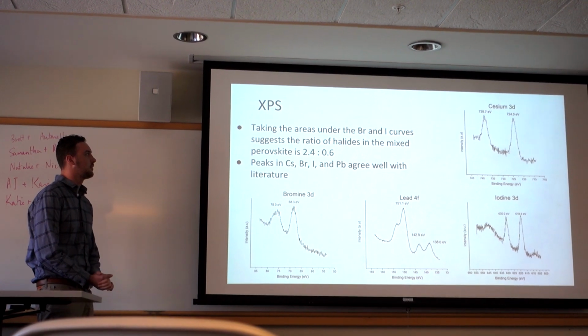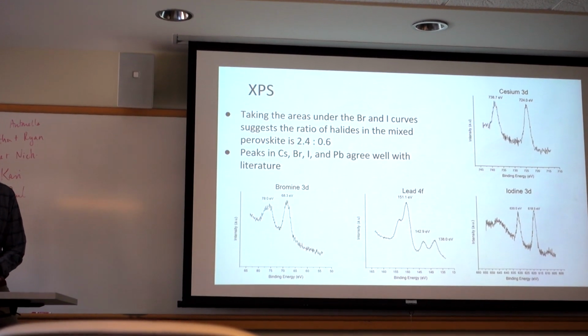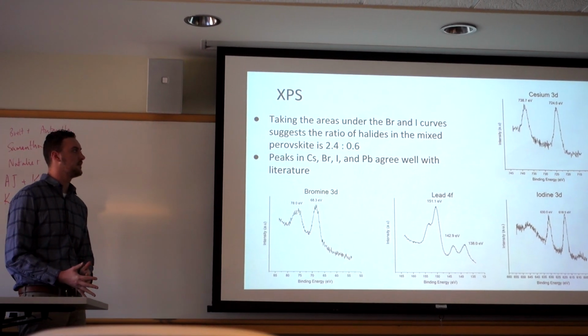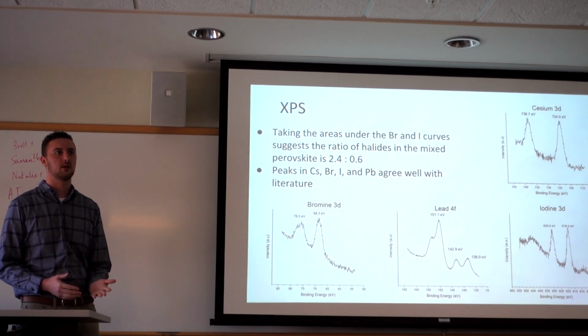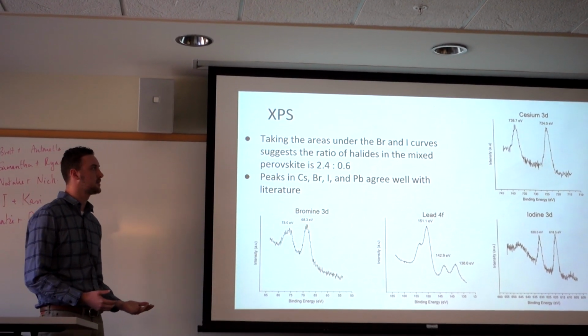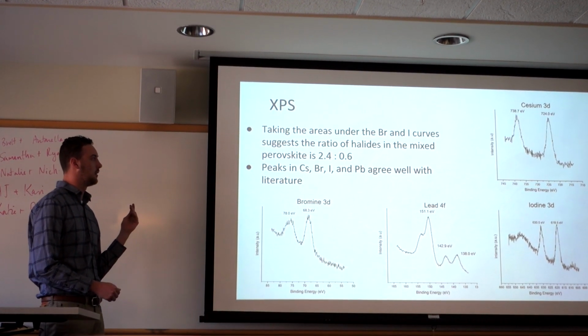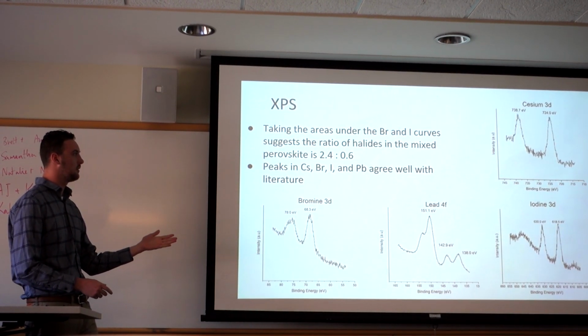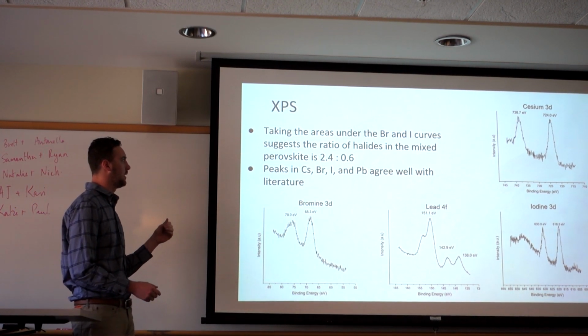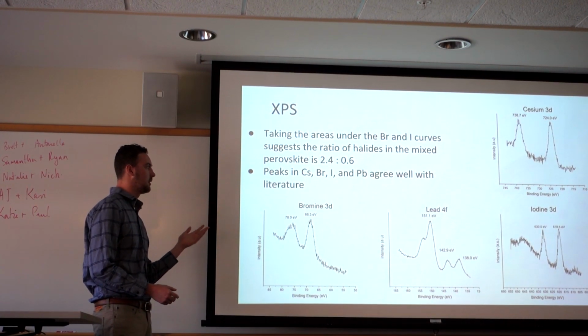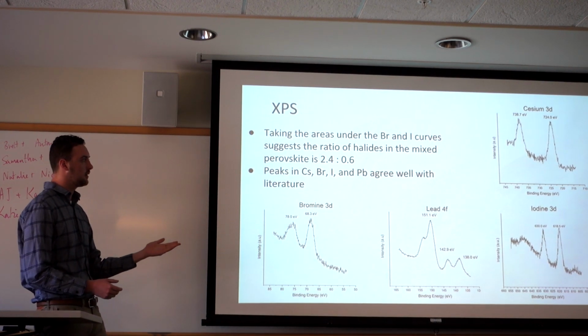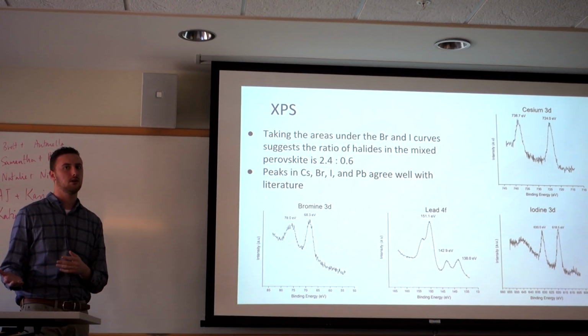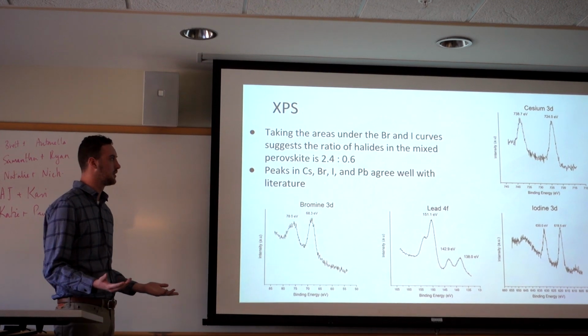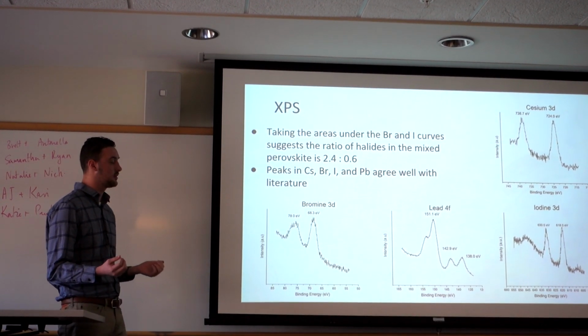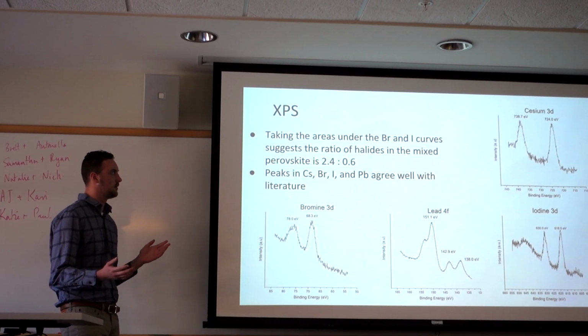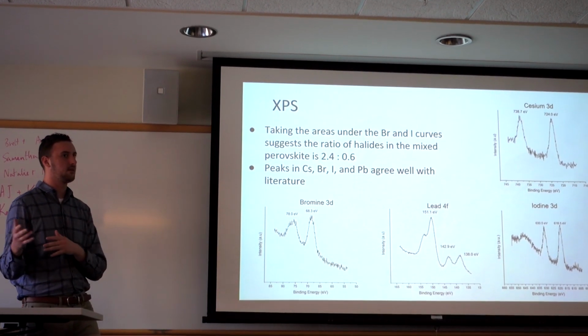So then we performed an X-ray photoemission spectroscopy experiment on our films. This tells us the chemical composition of our films. All the binding energies agree well with literature. And then we use the area under the bromine and iodine curves to determine the ratio of the halides in our mixture. And we determined this to be in a ratio of 2.4 bromine to 0.6 iodine.